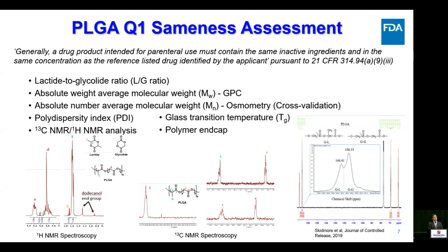At the start, most of the labeling describes the polymer composition. As Dr. Park mentioned, we just said PLGA, but PLGA itself is different. And so we have to figure out the lactide to glycolide ratio by carbon-13 NMR and proton NMR. In the bottom left and middle are typical spectra from the proton NMR and carbon-13 NMR, but I'm not going to dive into detail because the previous two talks already mentioned how to evaluate the lactide to glycolide ratio, and also in the first talk Dr. Lynd said how to figure out blockiness. And also you can see in the earlier labeling, the polymer end group information is important. And so you have to demonstrate what kind of polymer end cap the PLGA has.